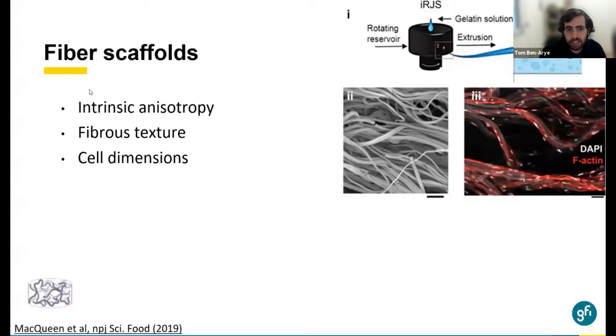So another option is fiber scaffolds, using either electrospinning or other techniques, or perhaps using some materials in nature that are intrinsically fibrous, such as fibers from plants or mycelium. They are favorable because they have an intrinsic anisotropy. They are basically fibers in the realm of the cell dimensions, and that's important because if you can functionalize them, you can really tune the behavior of the cells, not the average cell, but each specific cell, at single fiber resolution. And that's quite interesting, perhaps generating different fibers with different cell types and so on. And they also generate a very interesting fibrous texture that is important for cultivated meat and alternative proteins.